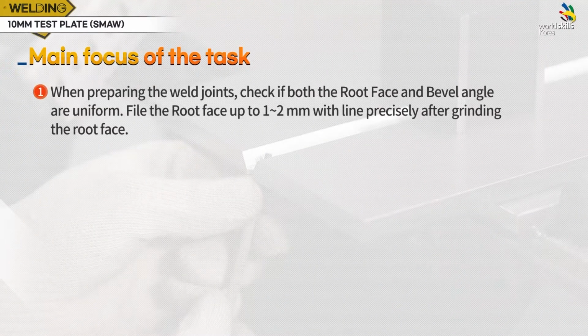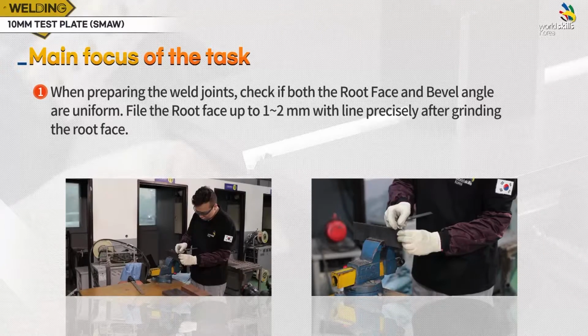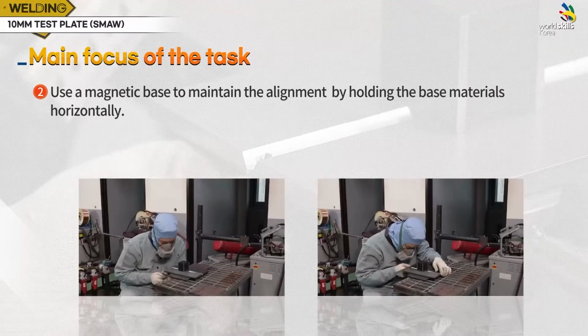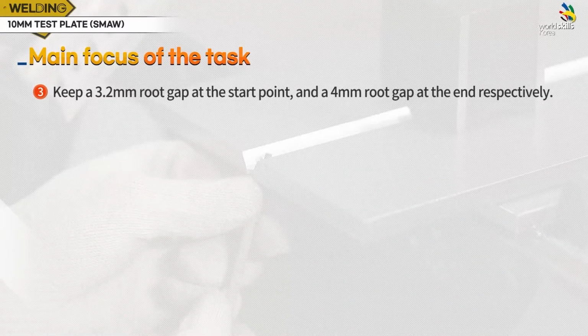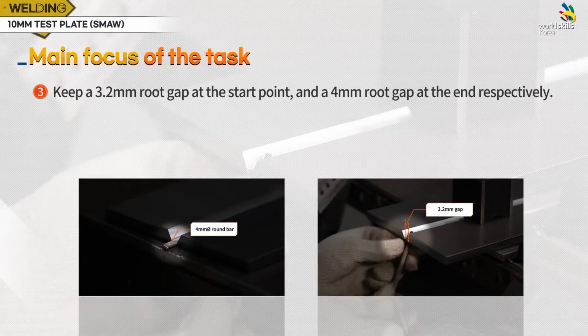Main focus of the task. When preparing the weld joints, check if both the root face and bevel angle are uniform. File the root face up to 1 to 2 mm with the line precisely after grinding the root face. Use a magnetic base to maintain the alignment by holding the base materials horizontally. Keep a 3.2 mm root gap at the start point and a 4 mm root gap at the end, respectively.